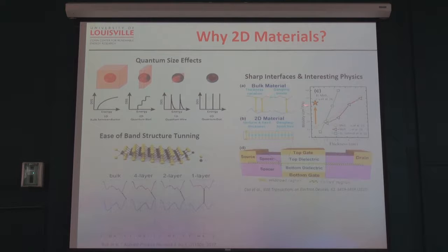Another thing is 2D materials are very important to study something called interfaces. If you have two materials making an interface, with a 3-dimensional material the thickness changes throughout the material. You see here one thickness, and at a different position you have a different thickness. But if you have a 2-dimensional material, it is very uniform throughout. So that makes it more interesting to study the interfaces. Here you can also see that depending on the thickness of the 2D material, your mobility can change. The mobility is given in centimeters squared per volt second, and you can see how it changes with thickness. They are not extremely large numbers, but compared to gallium arsenide, this is a reasonable mobility number. But much smaller than the graphene number. Graphene has much higher mobility.